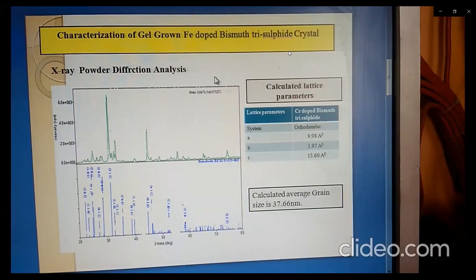and preferable hkl values, the lattice parameters a, b, c are 9.98 angstrom, 3.97 angstrom, 13.60 angstrom, and the axes are perpendicular, which shows a not equal to b not equal to c. From this, the grown crystal has an orthorhombic structure.